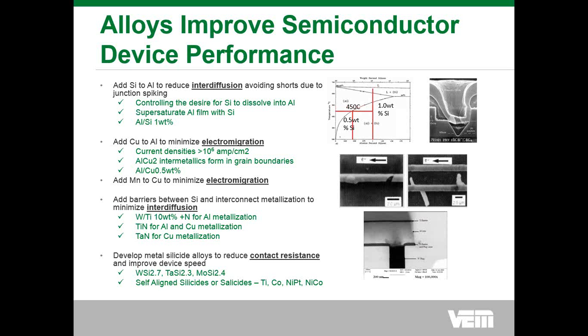producing a failure called junction spiking. So in order to minimize or eliminate that problem, the thought was, how about if we supersaturate the aluminum? By supersaturating it, if you put 1% by weight silicon, you won't have this problem, because you will eliminate the desire for that interdiffusion to occur because you've supersaturated and the chemical driving force is no longer there. So this is where the aluminum 1% silicon alloy was developed.